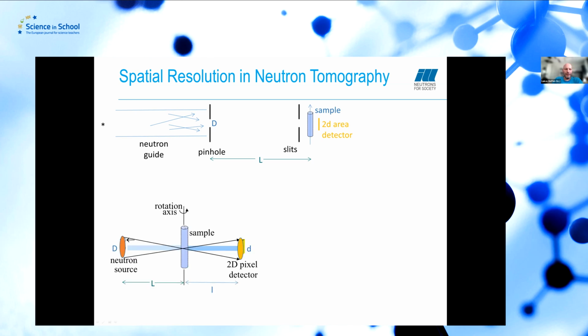And so the problem is, of course, when you put the detector at a finite distance, you will get some blurring, which depends on the collimation ratio that I've just said. So the relationship, because of the similarity of these triangles, is that L divided by D, the diameter of the pinhole, is the same as the detector distance divided by the blur circle.